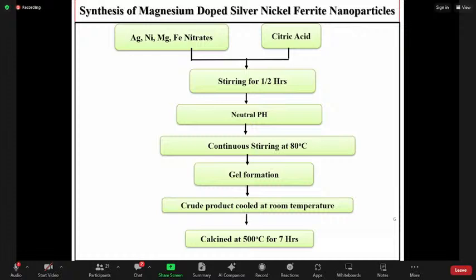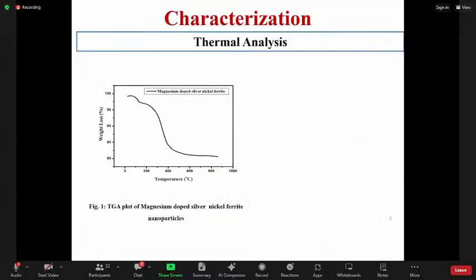After the gel formation, there is a crude product. I have cooled it at room temperature. After that, I have calcined it at 500 degrees Celsius for 7 hours. Here, the most important point is about the calcination. I have taken this temperature, that is 500 degrees Celsius, with the help of the characterization, that is TGA, because I have got my thermal analysis.